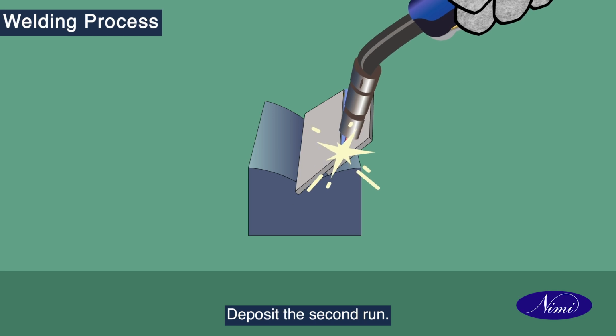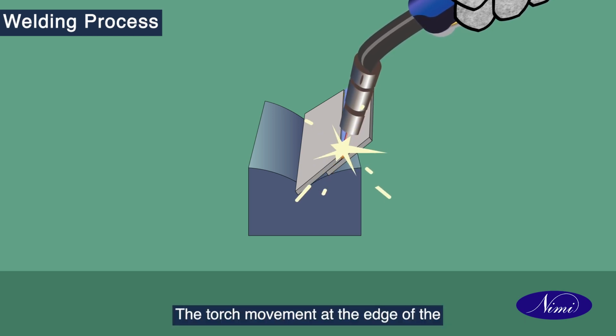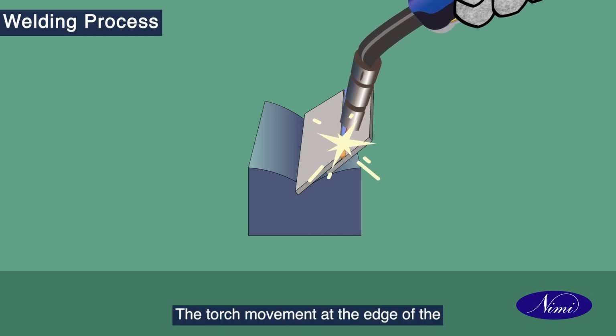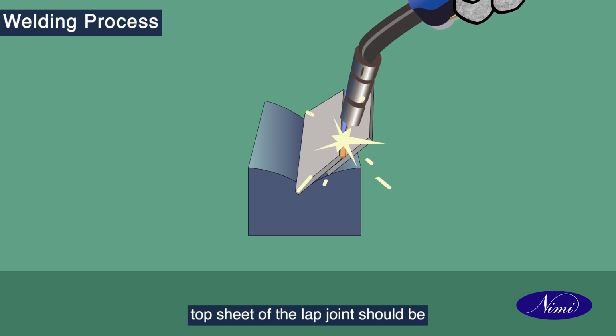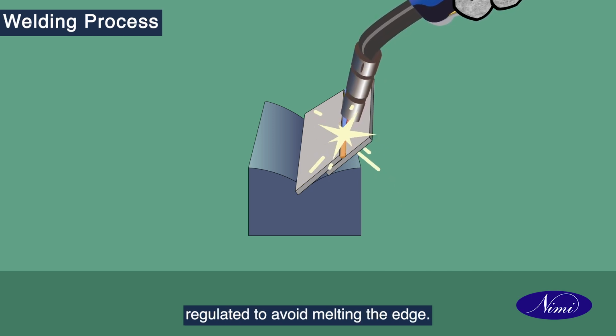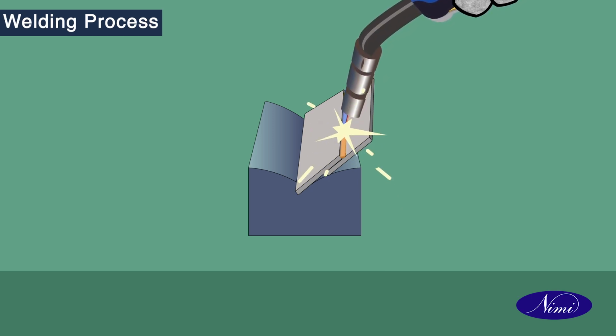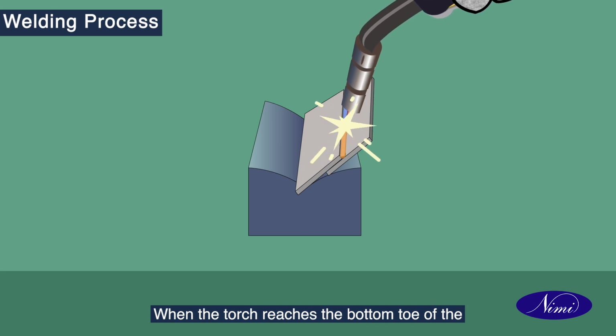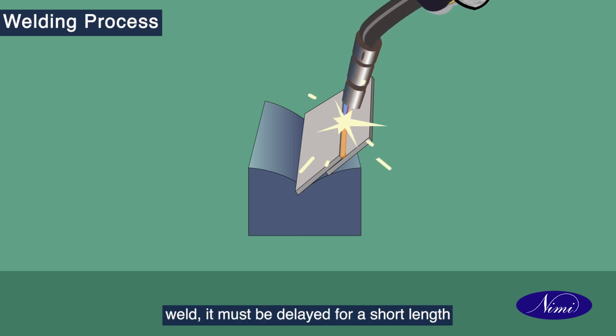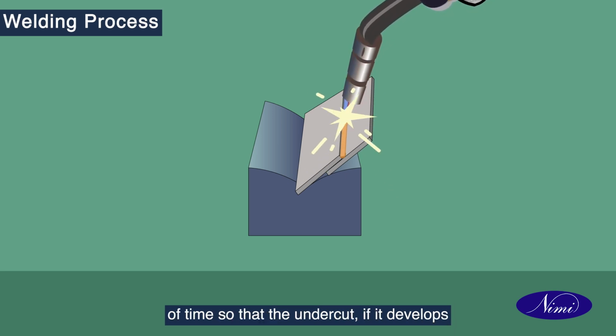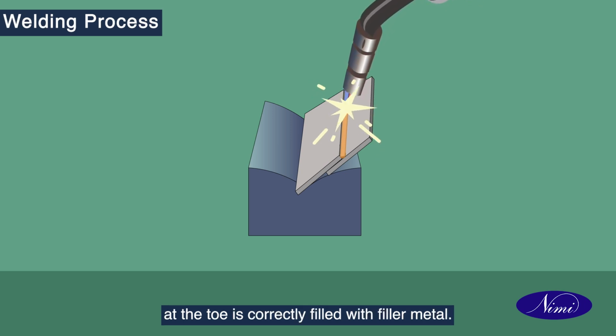Deposit the second run. The torch movement at the edge of the top sheet of the lap joint should be regulated to avoid melting the edge. When the torch reaches the bottom toe of the weld, it must be delayed for a short length of time so that the undercut, if it develops at the toe, is correctly filled with filler metal.